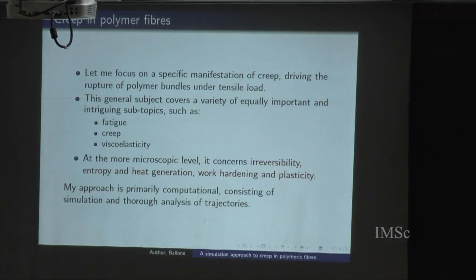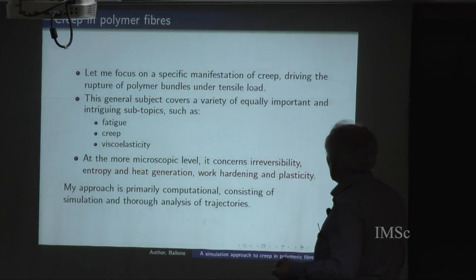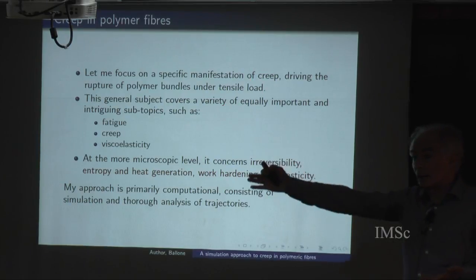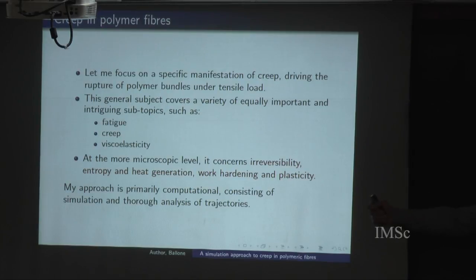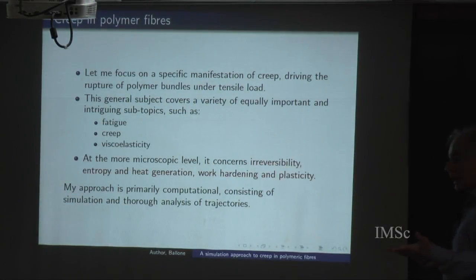Polymer fibers are a soft material in which temperature plays an important role, and so I'm looking at the bundles of polymeric fibers that fail under a tensile load over long times. We are not just stretching under a large force. We are far below the limiting force for breaking the sample at once. We are looking at the process of thermal fluctuations that break bonds and chains. And so what we are looking at is creep, but also fatigue, that is a frequency-dependent manifestation of similar phenomena.